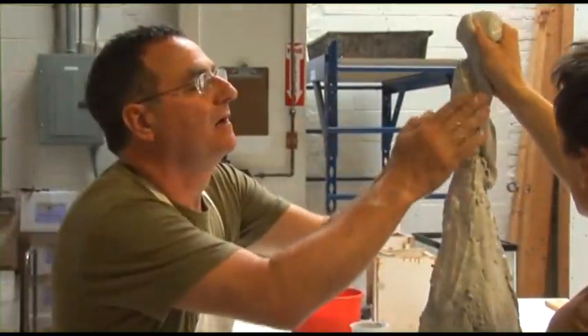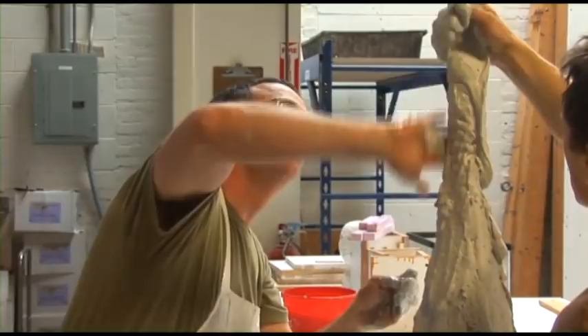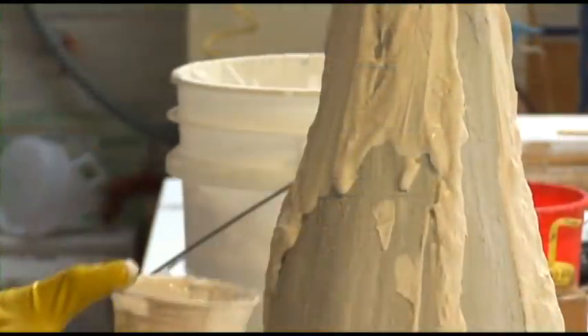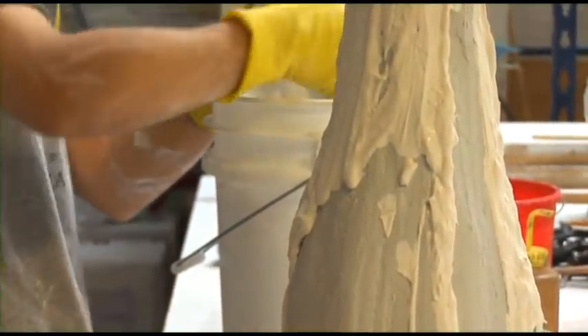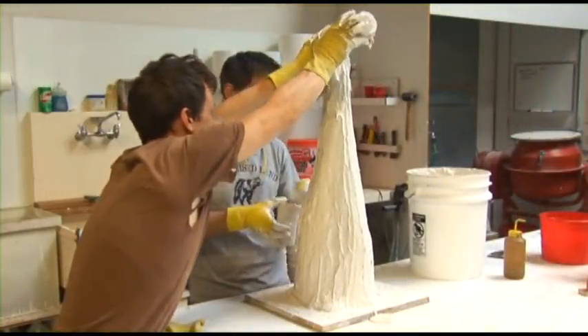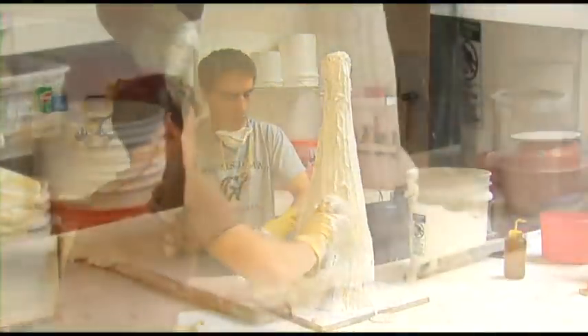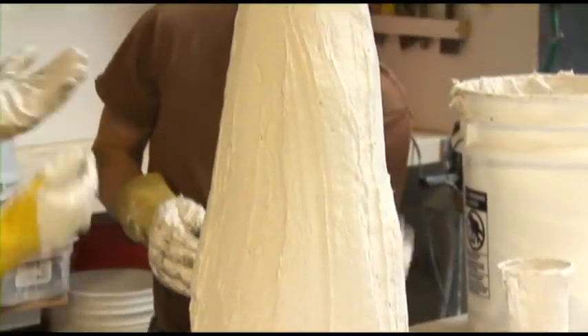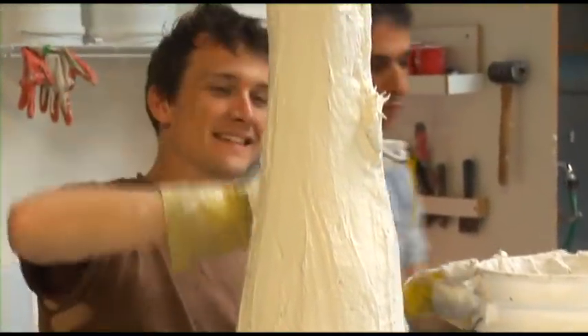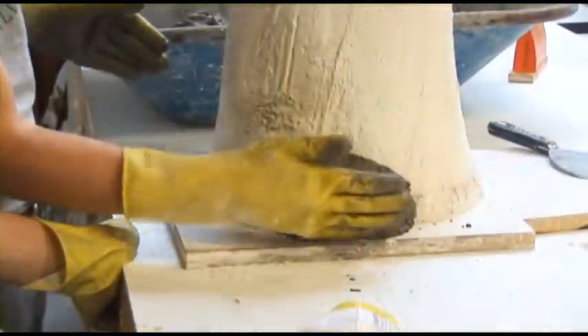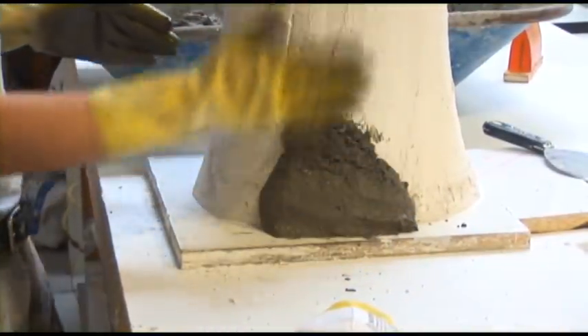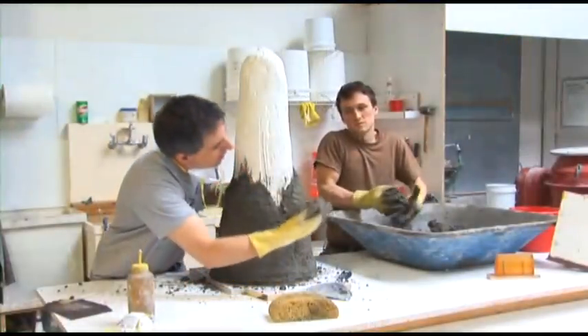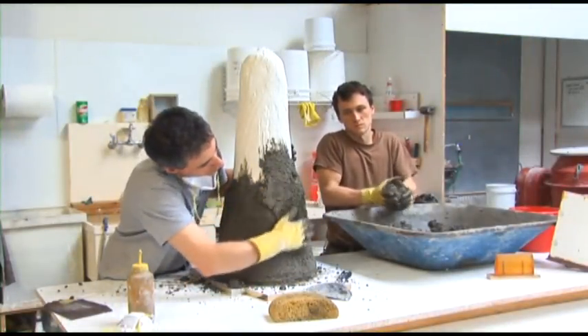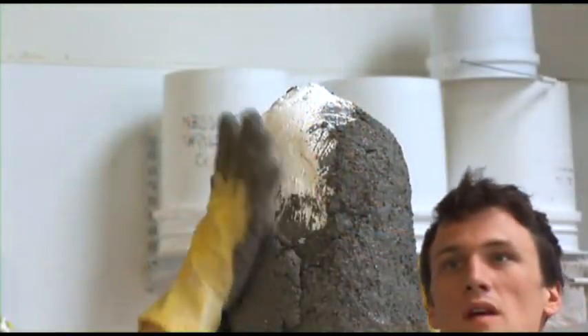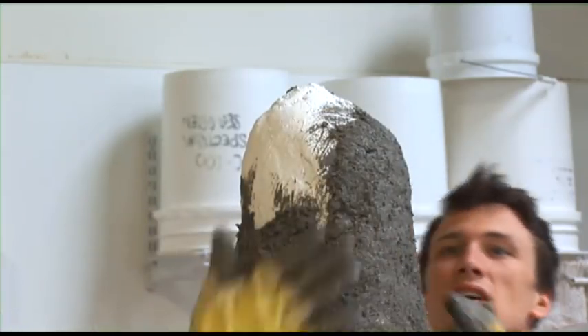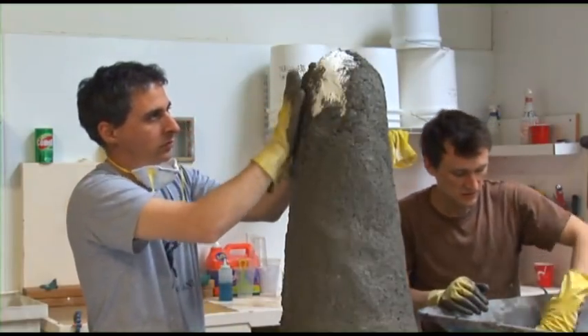Why is there the inner layer? Very early on I discovered that if you put the cement right against the dental plaster, it gases and makes defects in the glass. And through a lot of experimentation, I figured out that if you just put an interlayer, which helps to strengthen everything, then you don't have that same problem. The last layer is a kiln cement called KS4, and it's a 3,000 degree kiln cement made for making industrial furnace parts. And we use it because it is bulletproof.